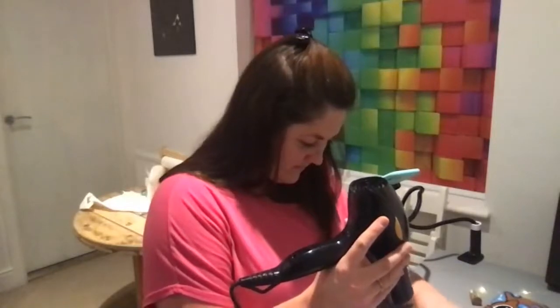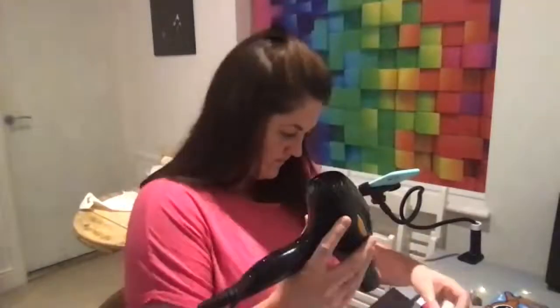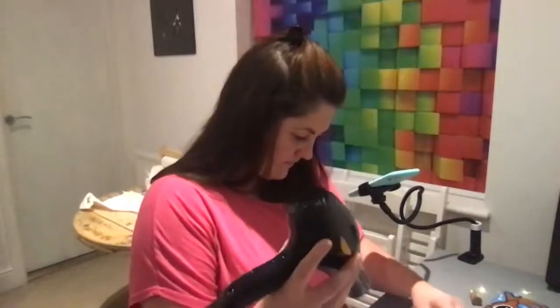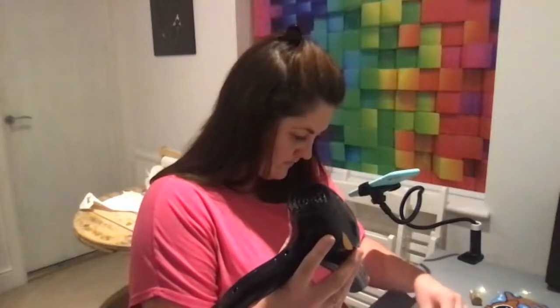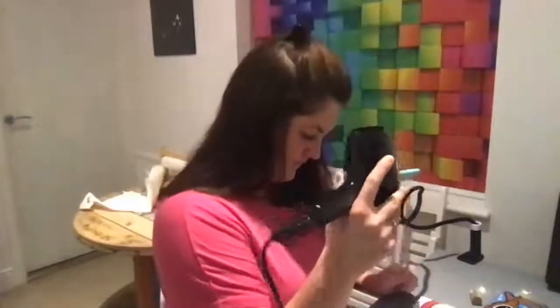How full on do you want the hairdryer? Low, sort of. Not the big fan or the medium fan. So the kind of the medium fan. So you want it hot, but if you have it too close, it will kind of blow your glaze away into ripples. So you want it to be hot when it hits the tile, so on a hot heat, but a kind of a low speed fan.